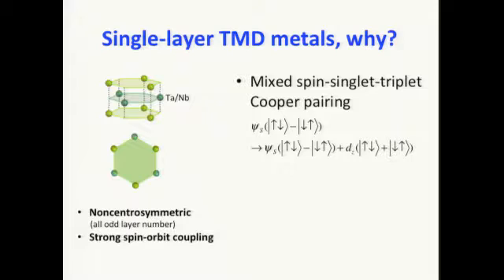Most relevant to my talk is the property of superconductors. In this material with non-centrosymmetry, as well as strong spin-orbit coupling, the Cooper pair wave function can no longer be distinguished by the parity operator, meaning that the parity eigenstate is no longer the energy eigenstate of the system. So the Cooper pair wave function, instead of a pure singlet state, is actually turned into a mixture of spin singlet with a spatially even wave function and a spin triplet component, which is a spatially odd function. I denote it as dz here.